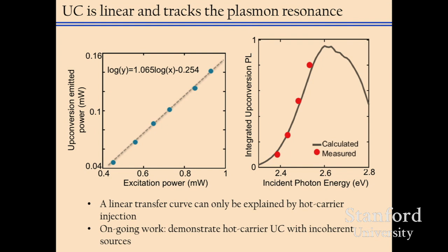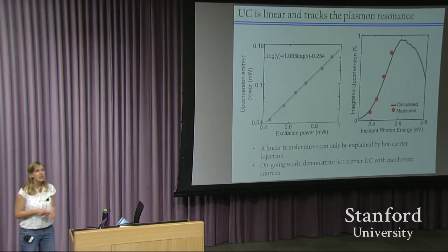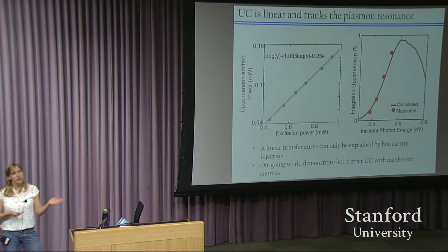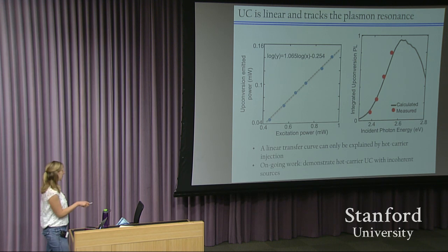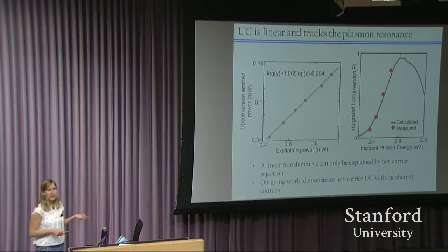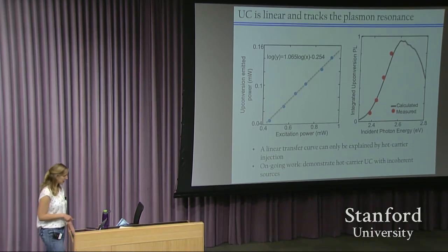So we can look at the power dependence and also the upconversion spectral dependence. The main takeaway message from this slide is that the upconversion emitted power is linear, unlike most other upconverting systems where you have this x squared power dependence. So this linear transfer curve can only be explained by hot carrier injection, and basically allows us to get more efficient upconversion with very low illumination intensities or illumination powers. So all of these preliminary results were obtained with a laser. Our ongoing work is now demonstrating hot carrier upconversion with incoherent sources, and then moving on to show infrared to visible upconversion. Okay, so I promised that was my last slide.